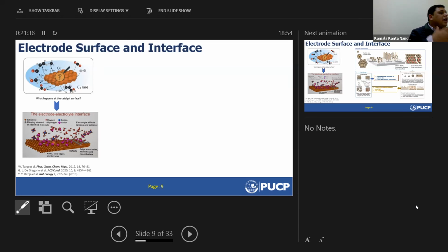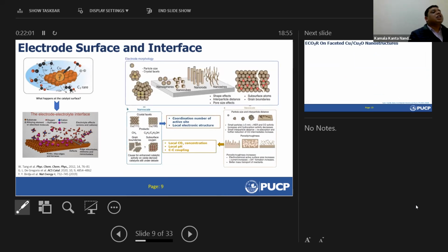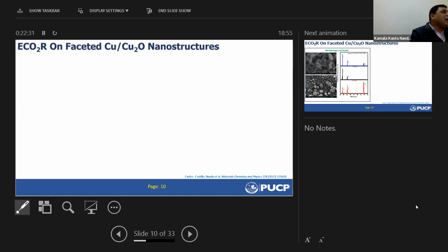The reaction occurs at the electrode-electrolyte interface, which has a galaxy of processes happening at the electrode: the required redox reaction, catalyst oxidation and reduction, and anions getting adsorbed on defects and the surface of the catalyst. All these processes occur simultaneously. So we have to design a catalyst in such a way that we can expose a specific facet and obtain a specific product. For example, if we synthesize a catalyst with a copper 111 surface, we will get specifically methane from CO2 reduction. If we go for 100, we'll get C2 products like ethanol and ethylene. Therefore, nanostructuring of the catalyst and identifying the facet that can give a particular product is important in catalyst design. Keeping this idea, we designed a catalyst for electrochemical CO2 reduction on a copper surface.